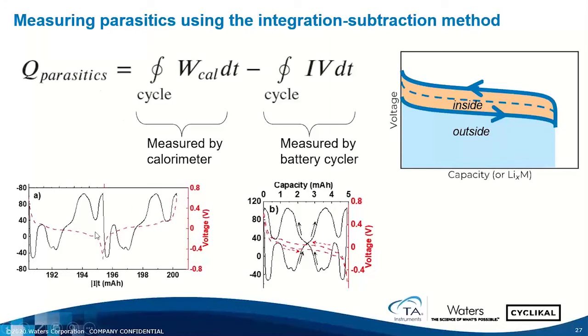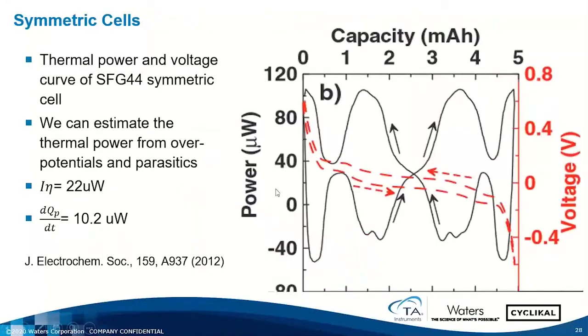So here is the thermal signal in black from a graphite symmetric cell. And here's the voltage curve. And if we wrap that around the switch point, we wind up with a plot like this. And that's highlighted on the next slide. This is the thermal power and voltage curve of a synthetic flake graphite symmetric cell. And you can see the symmetry involved in it, which underscores Vincent's point about having symmetry in the cell and the ability to apply this integration subtraction technique by canceling out the entropic terms. And these large features here are indeed due to entropic terms.